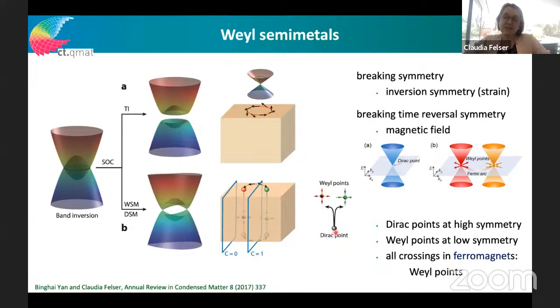And the nice thing about these Weyl points is they have chirality, and they more or less act like a source and sink, like magnetic monopoles. So there are 2 ways to transform a Dirac point into Weyl points. One is simply to strain my graphene, which will not be so easy because it likes to be Dirac and doesn't want to become Weyl. Or we can make something magnetic, because then we break time reversal symmetry. And this is the second condition: despite having no inversion symmetry, we break time reversal symmetry, we have a magnetic material, or we apply a magnetic field to lift this degeneracy and turn the Dirac point into 2 Weyl points.